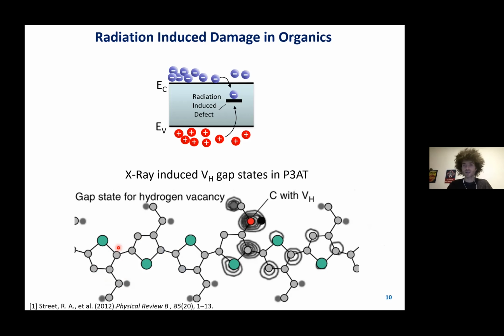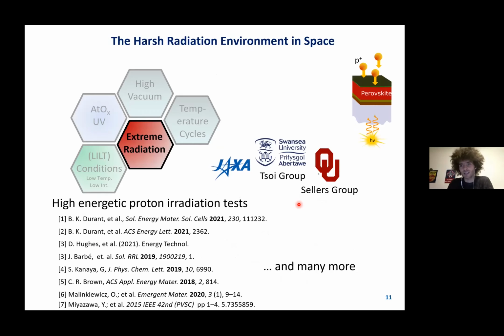Then one last example now from the organics. And here I'm just taking P3HT as an example. And upon irradiation, it's well known that you basically break a C-H bond, and then the hydrogen moves around the backbone of the P3HT and is a defect there. But you can also anneal it to recover performance. All right. So enough examples. Let's switch over to perovskite.